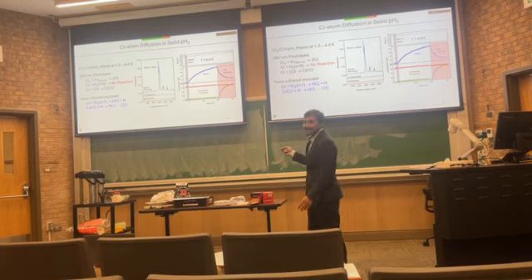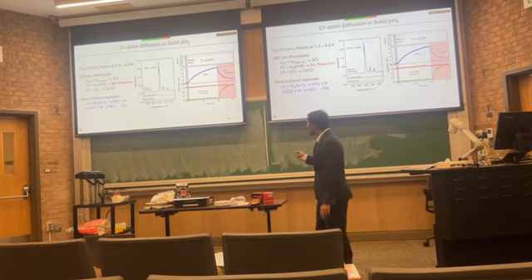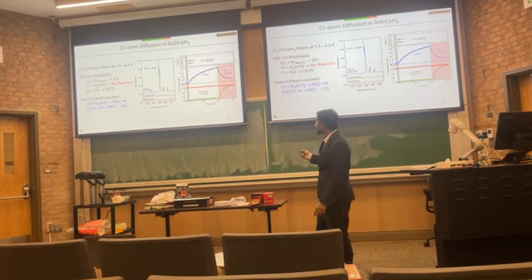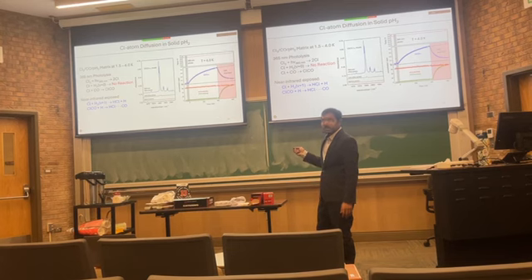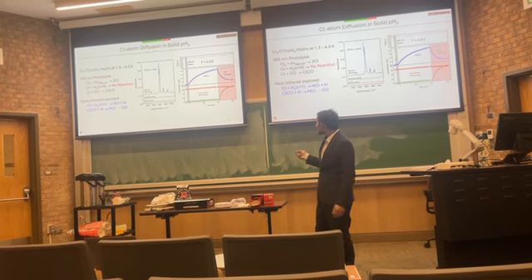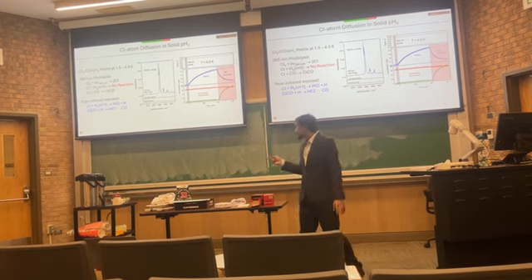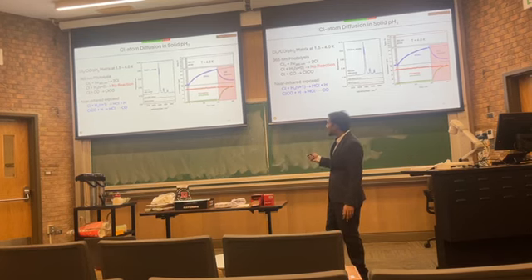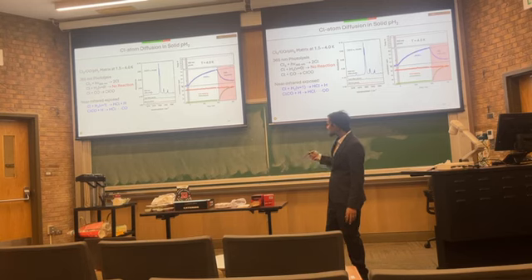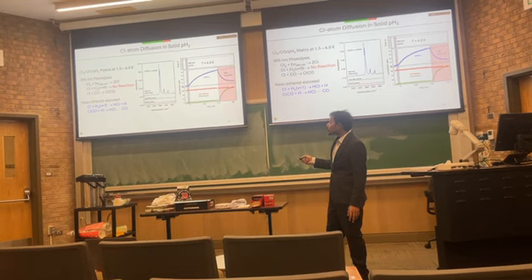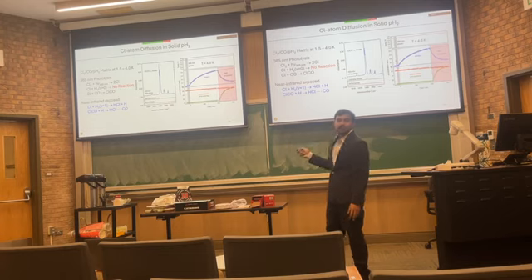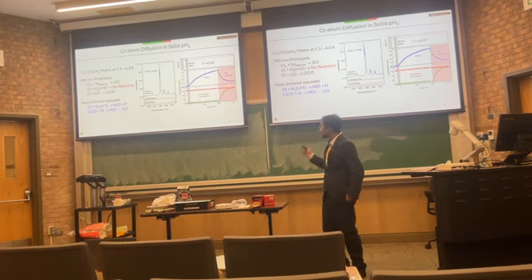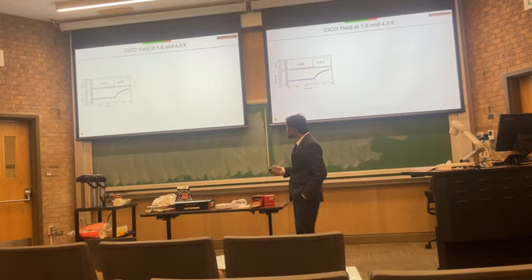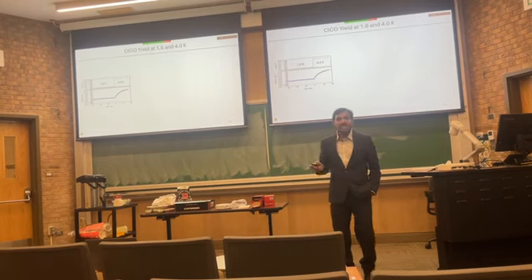We can do all the kinetics, I already showed you before, but another interesting thing happened. When we expose it to near infrared, those ClCO start to drop. It gets destroyed again. So near infrared not only allows this chlorine plus hydrogen reaction to make HCl, you see HCl is growing, it also somehow destroys our ClCO. We'll investigate that in the next few slides. Before going into that, let's look at the temperature.